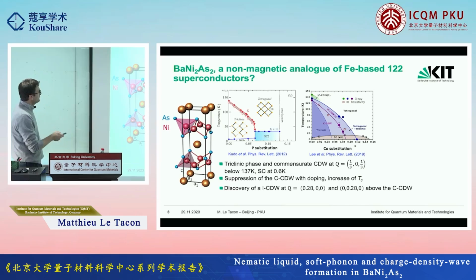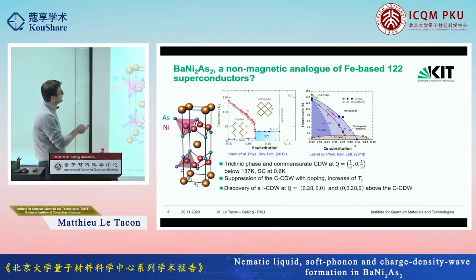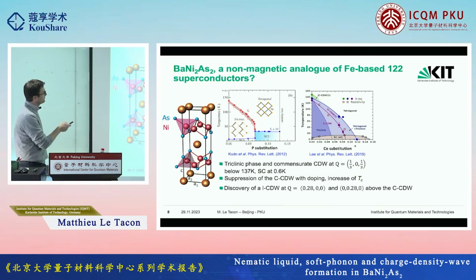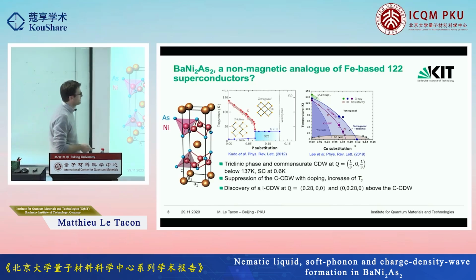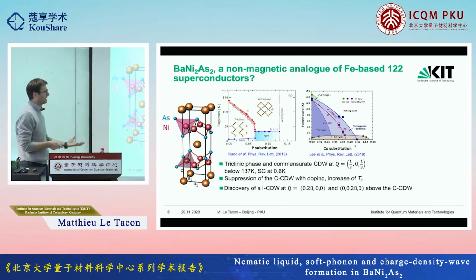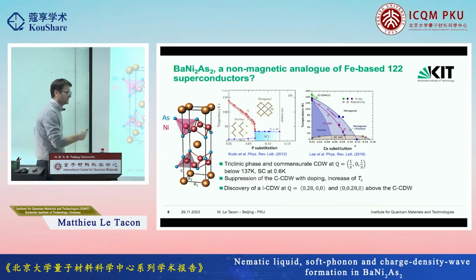And so this is a bit of a sad story because, you know, when you cool down that system, what you find is a strongly first order transition around 140K. That's interesting, by the way, that this transition occurs pretty much at the temperature at which the iron one orders magnetically.